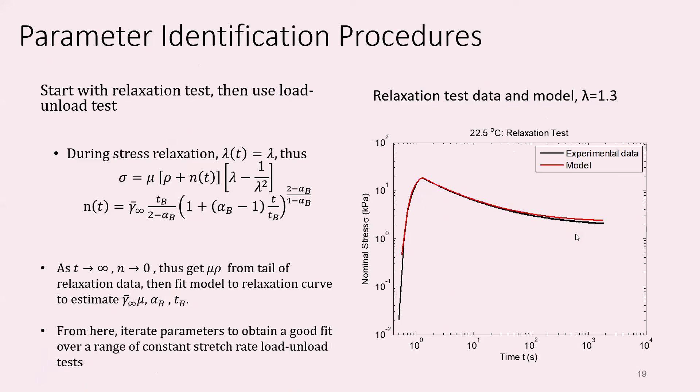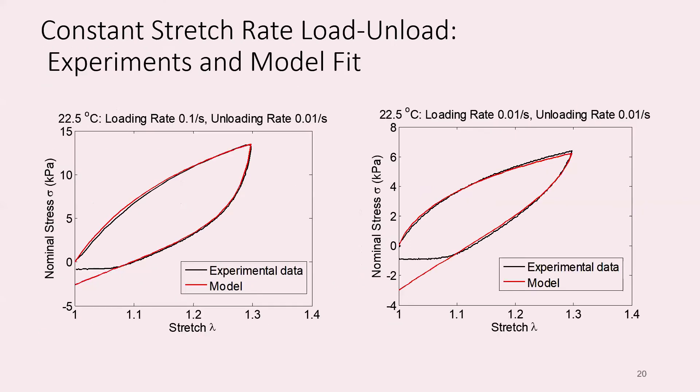When we do constitutive modeling and fitting, we're matching those parameters to the data. You can do a stress relaxation test where you stretch it to a certain stretch and hold it. We take the long-time modulus to be mu rho, then fit the other data to the relaxation test and iterate these parameters to get a fit to the loading and unloading test. Here's an example of the fit at two different stretch rates. The red is the model, the black is experimental data. The model doesn't consider buckling, which is why it goes into compression. But at least up to a stretch of one point three, we were able to model that data extremely well with this constitutive law.